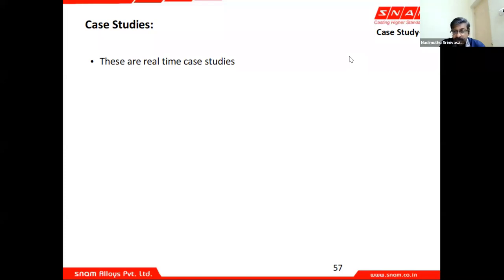I would suggest that you use the maximum pig iron that you can use, but some people say I'm going to use 100% borings. Please don't do that. See what is the maximum percentage of pig iron that can be used, because if you add a lot of CRCA, then you need to add the balance material also. You need more ferrosilicon. As I told you, in our Indian foundry ecosystem we have some constraints. We are not able to get very high purity charge material.